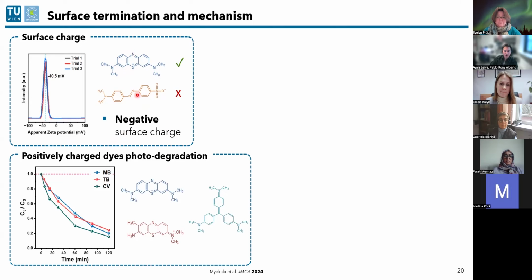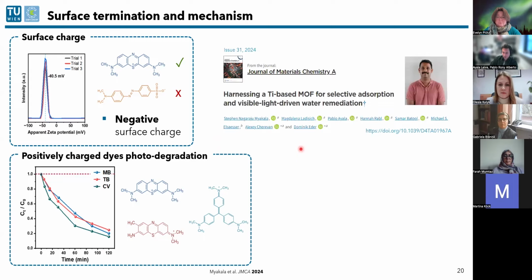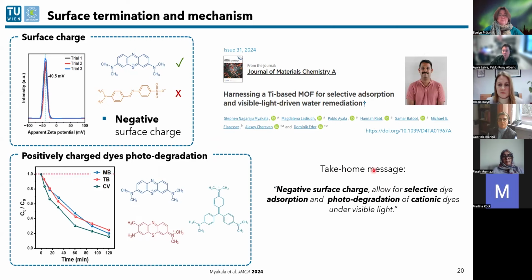To further corroborate this, we used other dyes that were positively charged and had different structures, and we saw that the concentration upon light irradiation was also dropping. This was quite a nice result, to have this selectiveness for positively or negatively charged dyes. This work was then summarized in a publication led by my colleague, Stephen. And here, maybe a short take-home message: this negative surface charge was very important in the selective adsorption of the dye, and this then enabled efficient photodegradation of these cationic dyes. So these particles were not only defect-free, but they also had ligand termination. So we were learning even more about this material with time.